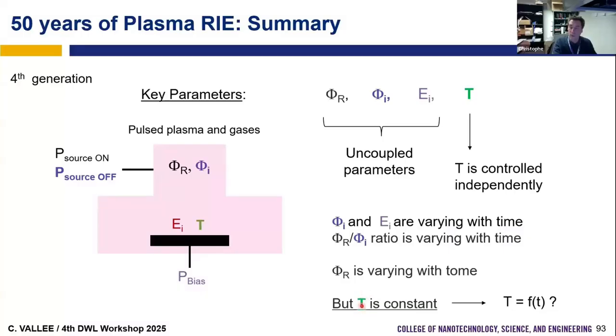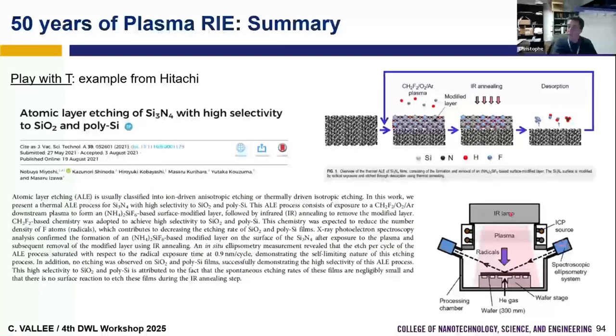So now we have new processes where we try to understand the impact of temperature, like cryo etching, but we don't have processes where we can vary it with time. And to my knowledge, there is only one very interesting tool from Hitachi, where they have some infrared lamp, so they can modulate the temperature during the process, because if you want to modulate the temperature with a substrate, it takes a very long time under vacuum to go from high to low temperature, so it's not possible. But they use this infrared lamp to have additional heating, so they can do an ALE process where they flow some gas to form a film on the surface, a solid film, and after they use the infrared lamp to heat this material and volatilize it, and they repeat, and they have an ALE-like process. By playing with the variation of temperature with time, we don't have the same temperature here as here, because during this process we use infrared annealing. So this is a good example of how we can try to add new processes by varying temperature with time.